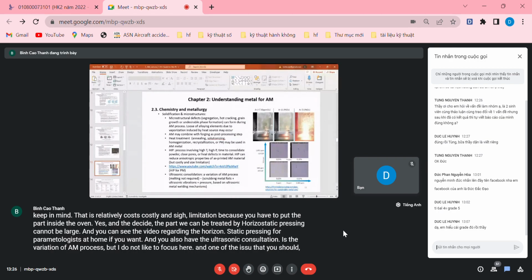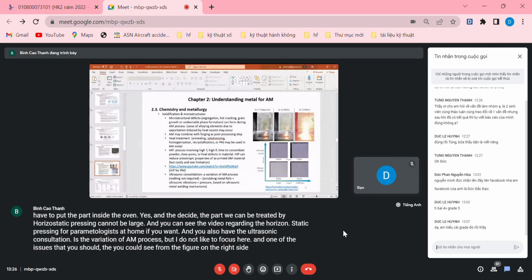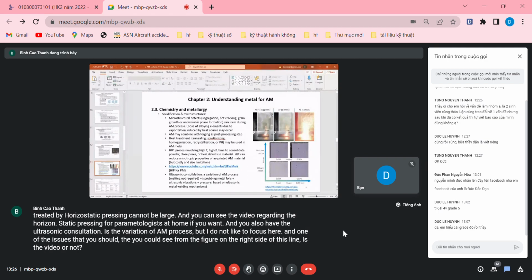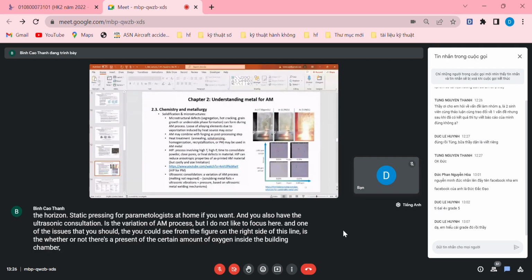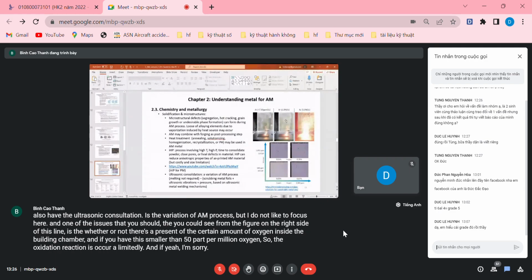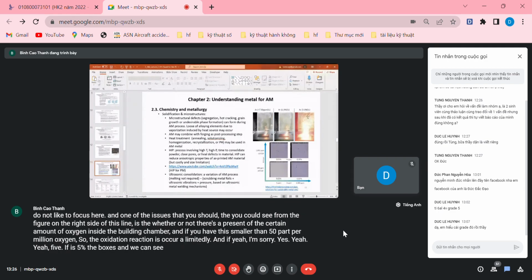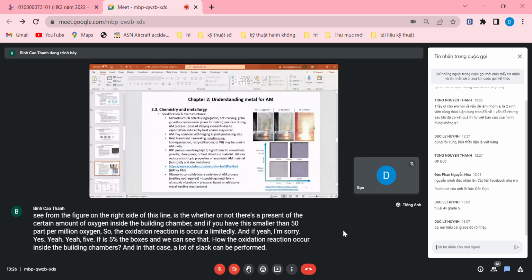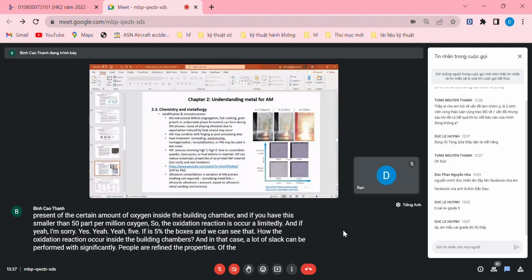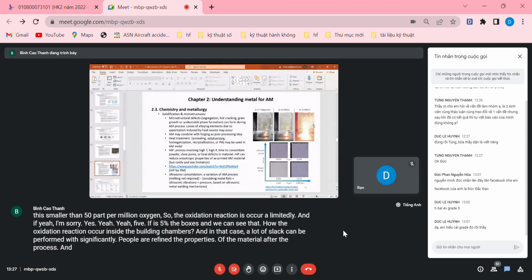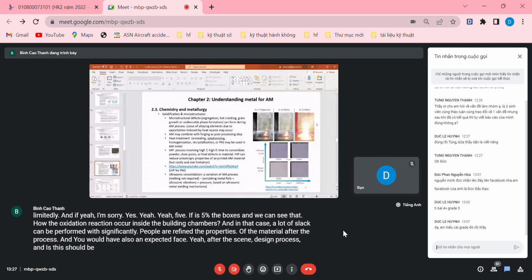And one of the issues that you could see from the figure on the right side of this slide is whether or not there is a certain amount of oxygen inside the building chamber. If you have smaller than 50 parts per million oxygen, the oxidation reaction occurs only in a limited way. If it's 5% oxygen, you can see how the oxidation reaction occurs inside the building chamber. In that case, a lot of slag can form, which significantly modifies the properties of the material after the process. You would also have an unexpected phase after the sintering process, and this should be avoided.